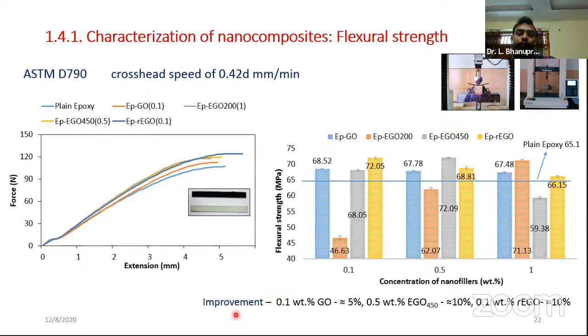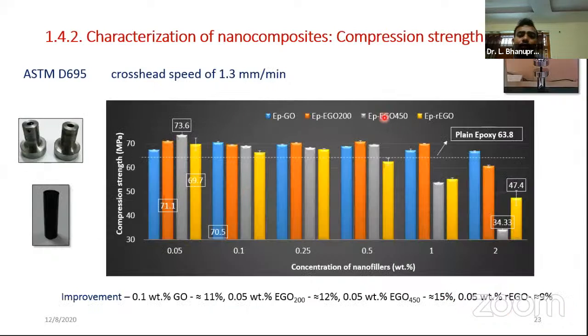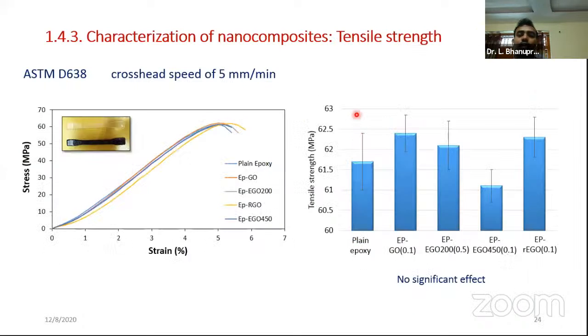We have noticed a good improvement, a good sign, at the nanocomposite level. We noticed improvement with the reduced exfoliated graphite oxide, REGO, and the EGO exfoliated case. A 10% improvement is noticed. And in compression also, we noticed up to 15% improvement with the exfoliated graphite oxide. And there is no effect on the tensile properties.